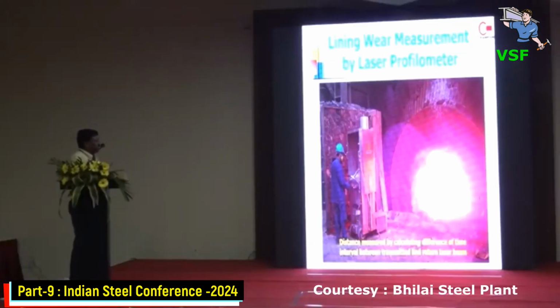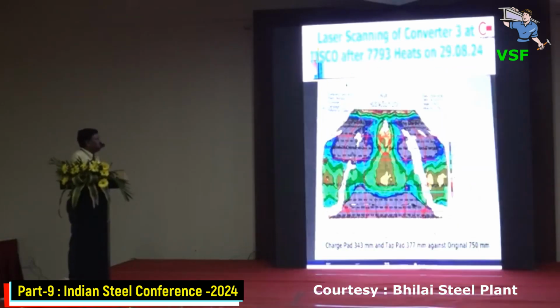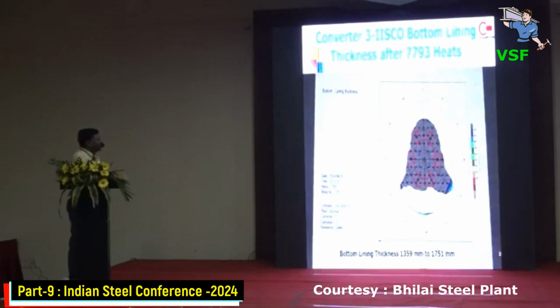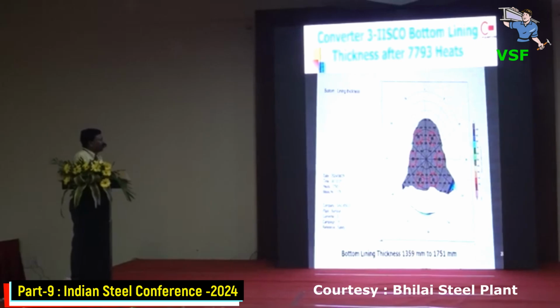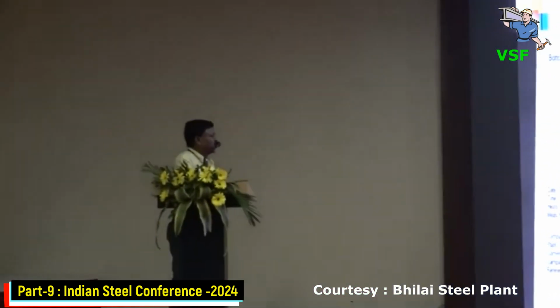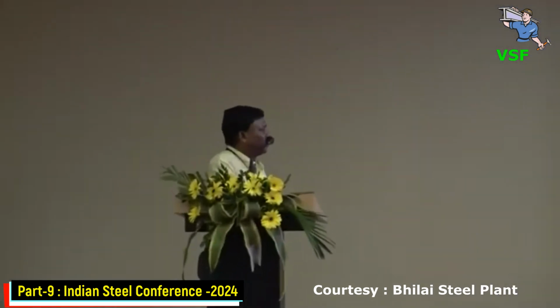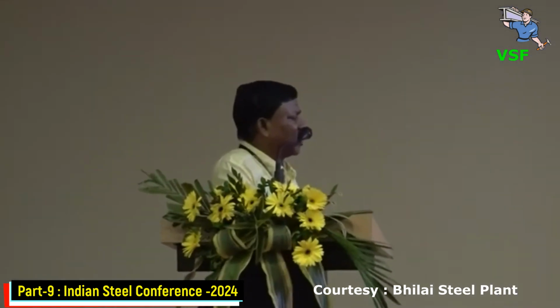And this is the laser profilometer being used, and this is the graph where you can find the taphole thickness as I mentioned. The charge pad is 343 millimeter, and the taphole is 177 out of 750. This is the bottom thickness we are getting, varying between 1359 and 1751. We are also doing the bath height measurement, along with the lance position, and the total volume is being maintained to maintain the H/T ratio.